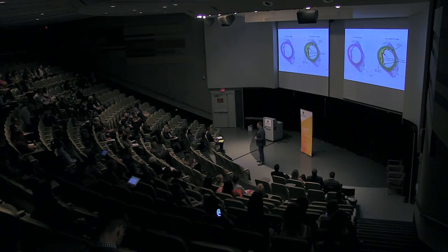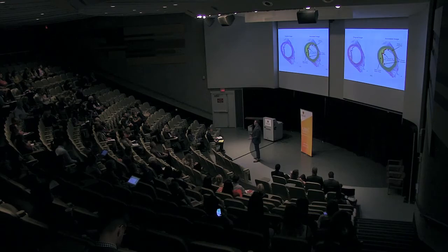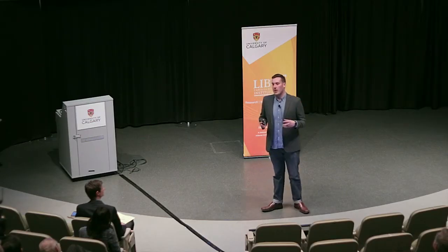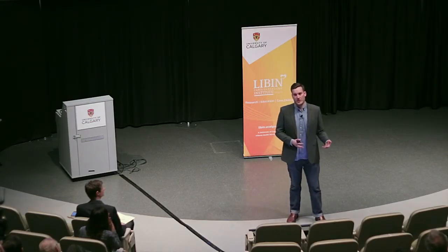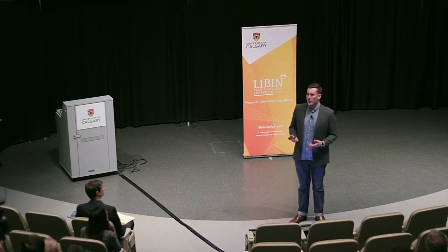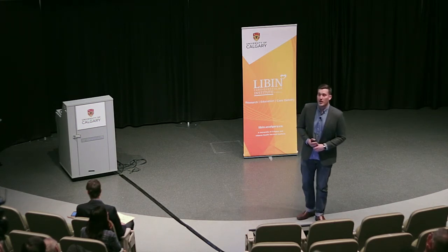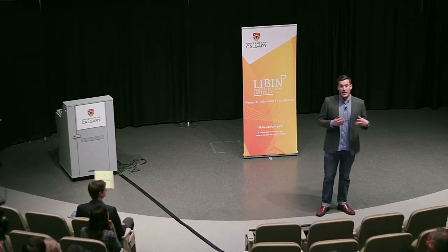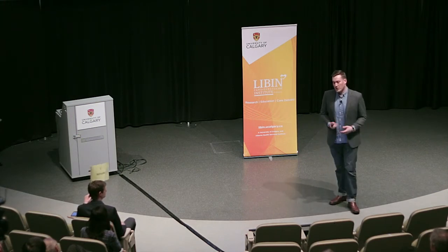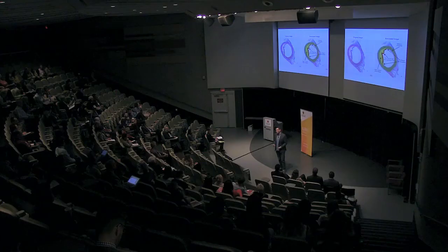And since we know that the strength of fibrous caps depends on the collagen content to a certain extent, and we know how these particles move through collagen gels, then by administering particles to a patient and looking at how they distribute themselves within these caps, we can predict collagen content and even rupture risk. So now, not only can we get an idea of the size and the geometry of the caps, but even their molecular makeup. Let's talk about another obstacle.